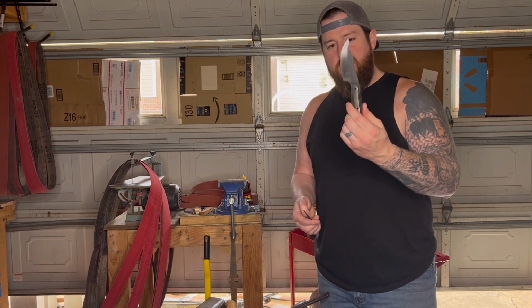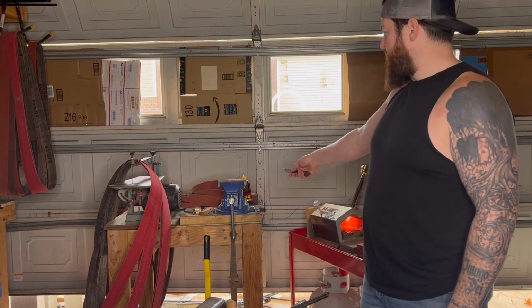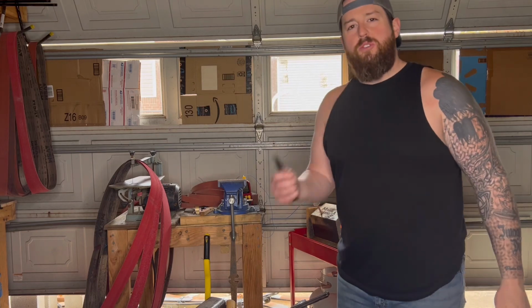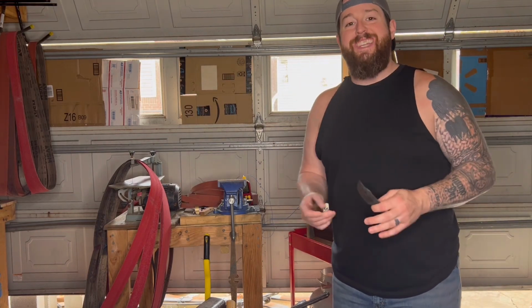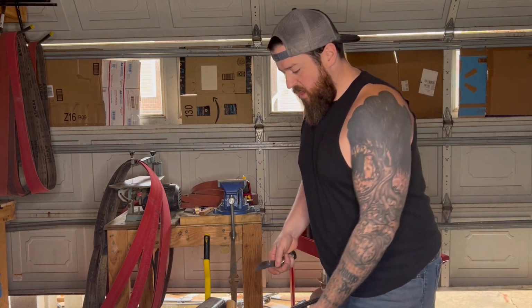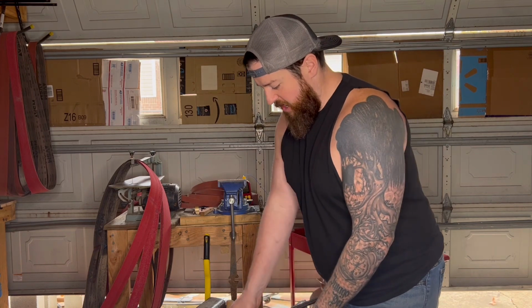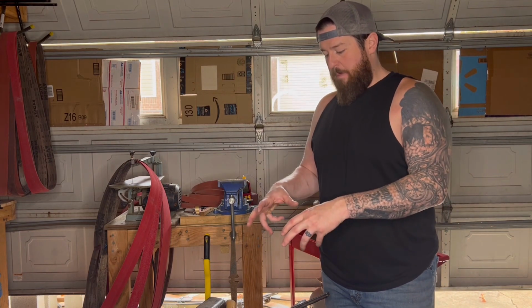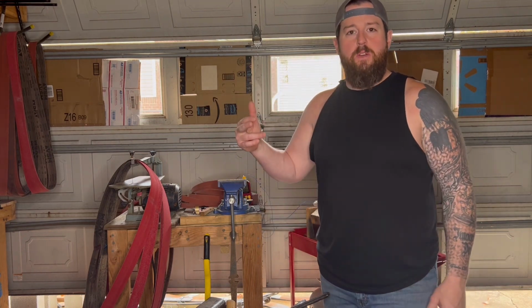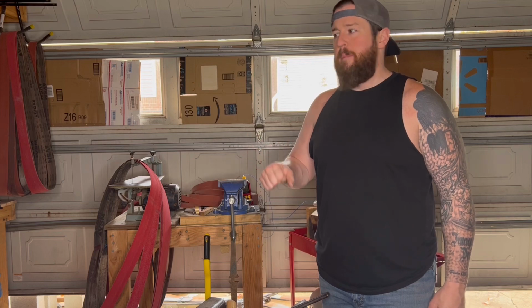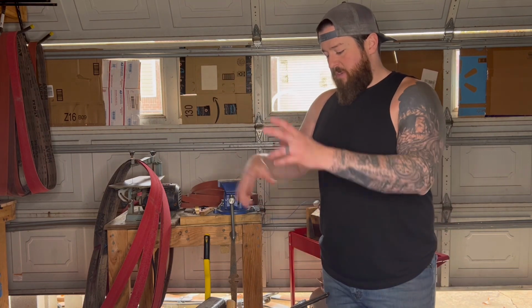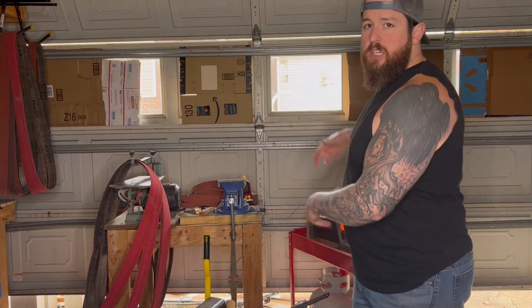What I will do with these knives is regulate the temperature at 1500 degrees in the forge. This steel will soak in there for 10 minutes. What that's doing is refining the grain. I've already done the first step of the heat treat process really when I finished forging. I put the steel back in the forge, bring the temperature up to 1700 degrees, and then I turn the forge off and let it cool off in the forge for several hours, usually overnight. Then once the grinding's done, I finish the heat treat process.